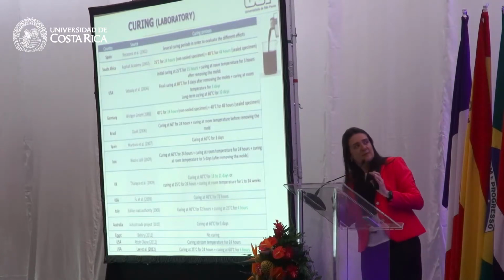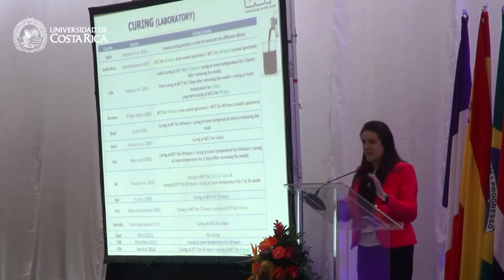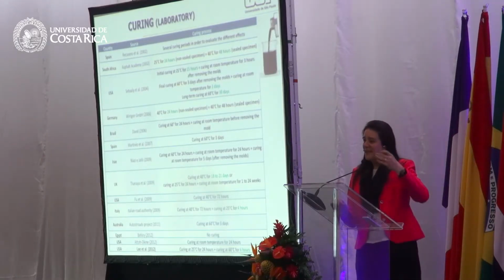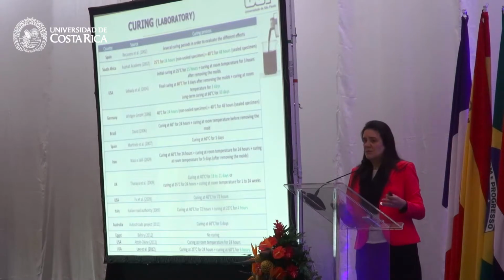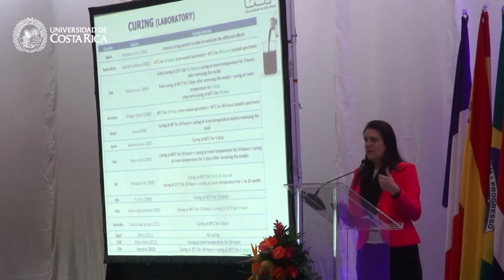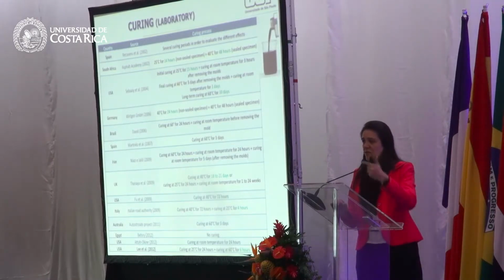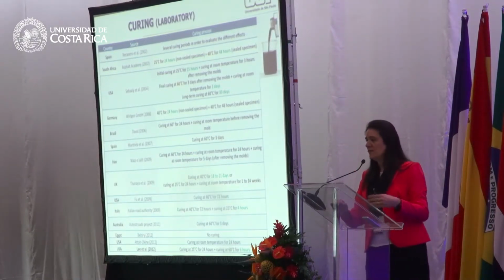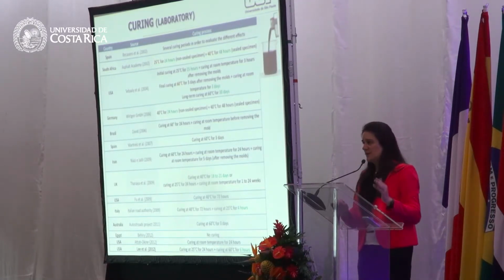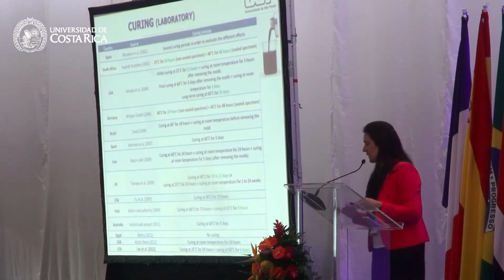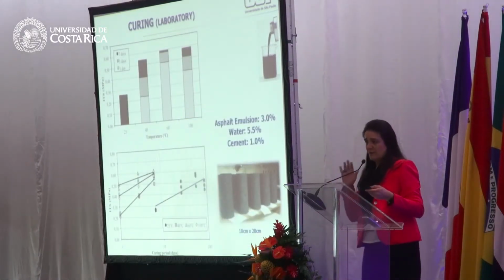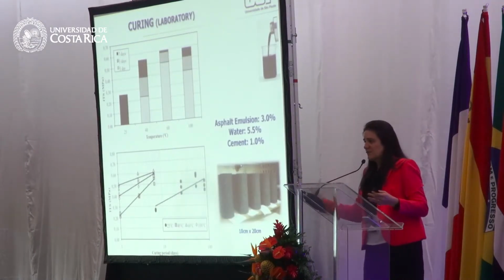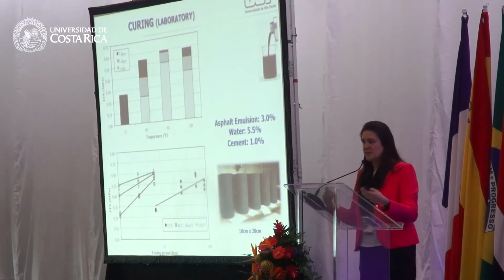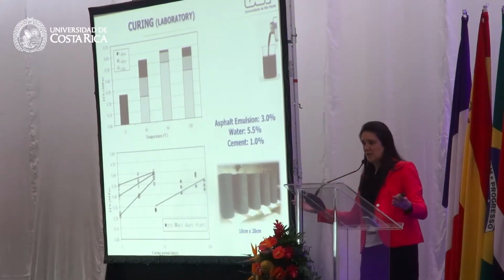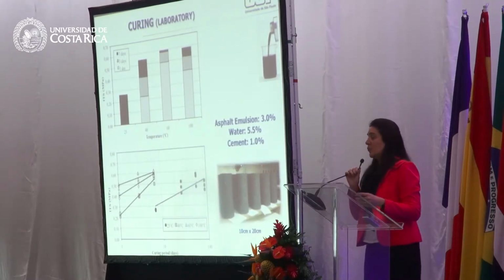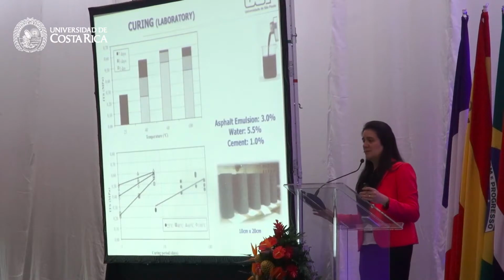I'm not guessing you are able to read this table, and you don't have to, but we've run a literature review just about the curing process, and you can find pretty much everything regarding the time and the temperature. So any research group does it in a certain way. We don't have a standard procedure that everybody is following, and this is an issue. Because of that, we know that the mix design cannot take forever. We cannot wait 1 month to have a mix design, so the job site stops at 1 month because we don't have the mix design. So we decided to make some trials to speed up this process.